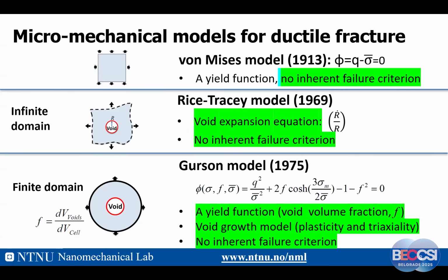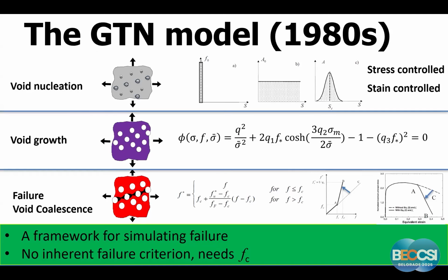So then let's go back to the most famous model, the GTN model. After the work of Tvergaard and Needleman, the Gurson model becomes quite capable. GTN becomes a quite capable model. It can consider void nucleation. So we could have a cluster nucleation, a continuous nucleation, or a statistical nucleation. It could be stress controlled, it could be strain controlled. And then we could have void growth. Void growth is from the Gurson model, so it's already there. Then the GTN model could consider void failure. But it provides a framework for considering void failure. It needs FC, the critical void volume fraction. There is no inherent criteria.